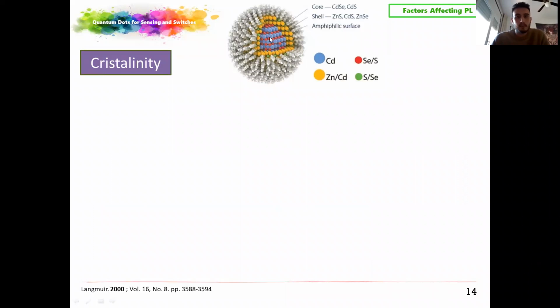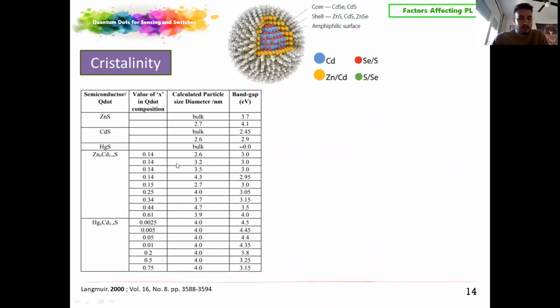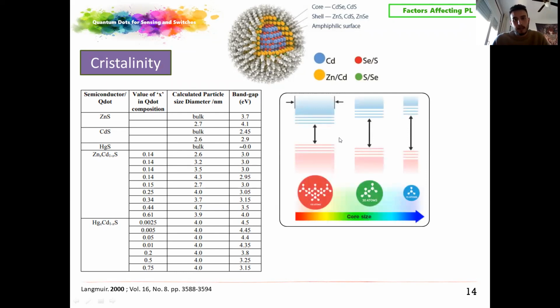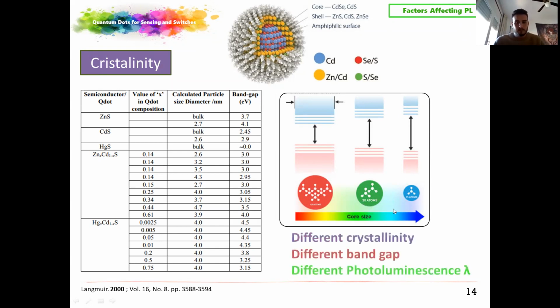Crystallinity is another property to be controlled. Here is a quantum dot. It's a semiconductor with a mixture of different elements, and you can modulate the proportion of the atoms of these elements in the nanoparticle. That promotes change in the band gap. And as I commented before, the effect of the band gap is so important to see what the emission wavelength of the quantum dot is. So different crystallinity can affect the band gap and modulate the photoluminescence wavelength.